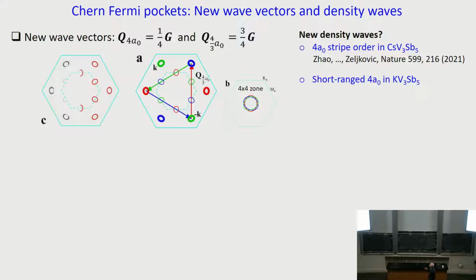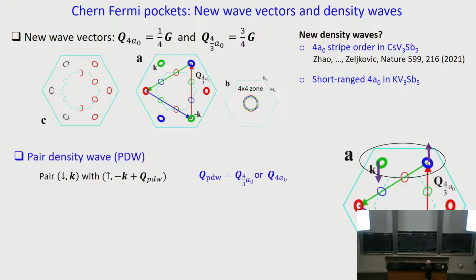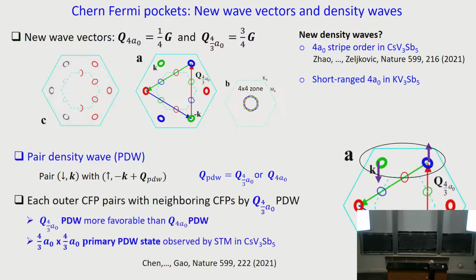And indeed, I'll show you STM sees some 4a0 stripes in one compound, the cesium-based one, and short-range 4a0 states in the potassium-based one. That's in the particle-hole sector. What about the particle-particle sector? Now you can think about pairing at zero momentum, but boosted by this lattice, these connections between the pockets. Then you would have a pair that carries a non-zero center-of-mass momentum, and that momentum would be 4a0 over 3 by 4a0 over 3. And this would be a pair density wave state.